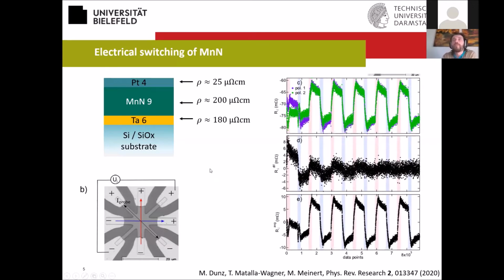And then we actually performed our switching experiments and find that we can manipulate the transverse resistivity that we observe here in our probe configuration by passing current pulses along either the blue or the red direction here. So we have these background colors here in red or blue, which encode passing the current along this blue arrow or along this red arrow. And then we have these white backgrounds. This means there is no pulsing. This is basically just a relaxation time, and we just watch the transverse resistivity evolve in time and relax.